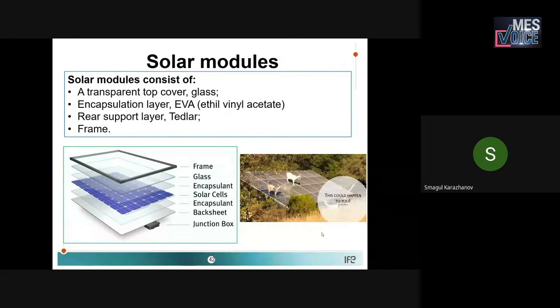Inside the module, there will be a frame and a protecting layer of glass. The solar cell will be encapsulated from both sides by an EVA layer, the encapsulation layer, ethyl vinyl acetate. Then the system will be heated to, I think, 110 degrees C, if I remember correctly. Then it will be melted and connected to the solar cell. Why this protection by glass is needed, you see on the right-hand side.